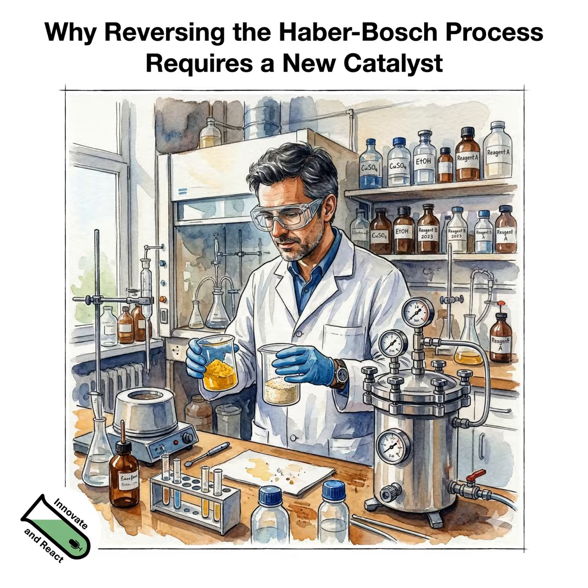Yeah. And on the synthesis part, to create this, you need a very well dispersed precursor. Otherwise, you get some big metal clumps in one part and just a lot of oxide in the other part. And ideally, it should be well dispersed. I said dispersed, but maybe dispersion is not the right term here, because in the precursor we can live with what we call a solid solution.